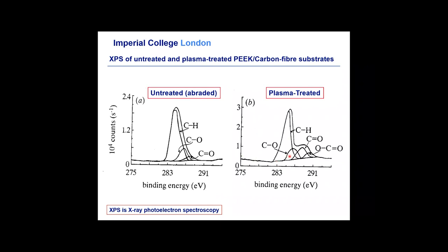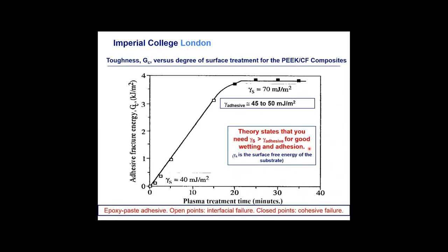After plasma treatment, here are the polar groups. You can see the concentration has greatly increased due to the plasma treatment and all those oxygen and ozone radicals. And here there's also an extra acid functionality. Therefore this surface treatment increases the amount of oxygen on the surface, and this in turn increases the surface free energy. And here's the proof of the pudding. Here we've made adhesive joints.